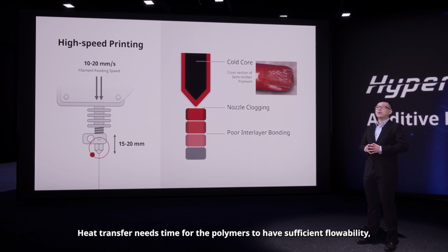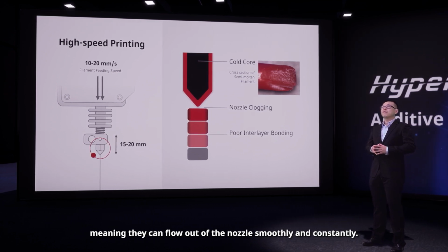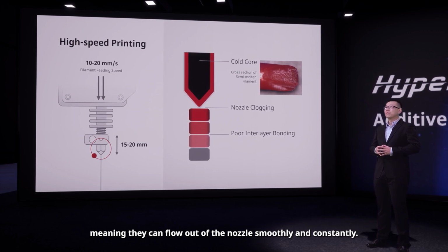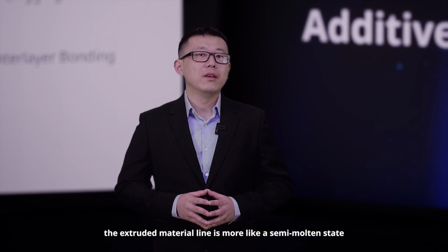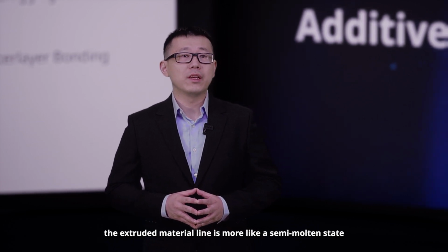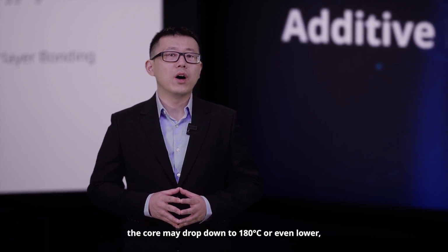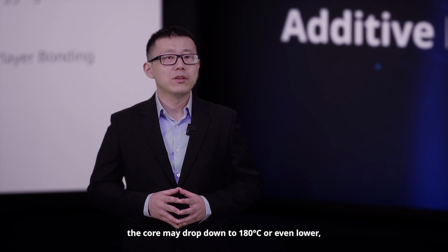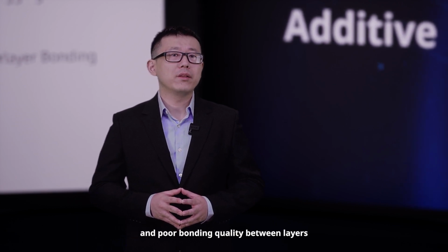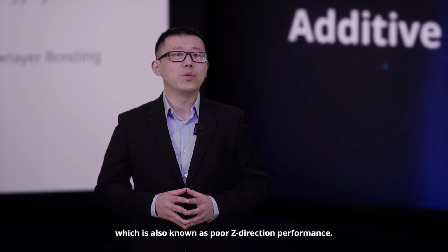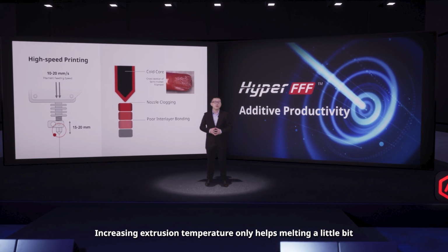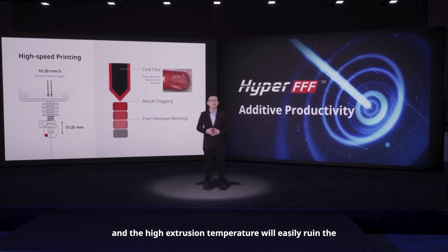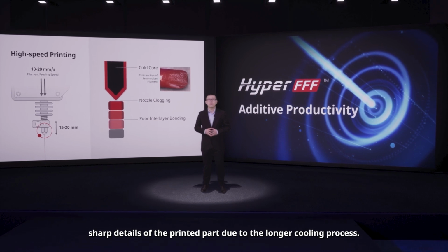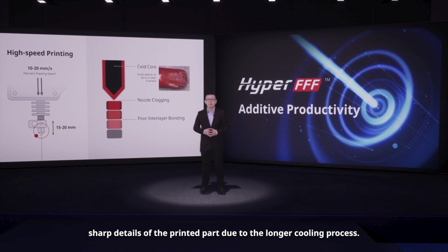Heat transfer needs time for the polymer to have sufficient flowability, meaning they can flow out of the nozzle smoothly and constantly. If the printing speed is too high, the extruded material line is more like a semi-molten state with a hot shell and a cold core. For example, for PLA printing at 220 degrees Celsius, the core may drop down to 180 degrees Celsius or even lower, which can cause nozzle clogging and poor bonding quality between layers, which is also known as poor Z-direction performance. Increasing extruding temperature only helps melting a little bit, and the high extruding temperature will easily ruin the sharp details of the printed part due to the longer cooling process.